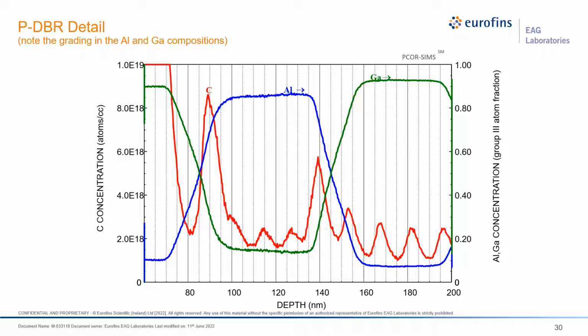As previously mentioned, grading the alloy composition between the low and high index layers can trim the resistance of the DBR. With our PCOR-SIMS technique, it is possible to hone in on this part of the structure with a higher depth resolution profile of the top 200 nanometers of the sample and reveal the composition grading. This occurs because the aluminum and gallium are not simply switched on and off, but varied in a precisely controlled manner to optimize the optical and electrical properties of the interfaces. You can see how the sloping blue line of the aluminum is not straight. It's actually formed in 2 discrete steps going up and 2 discrete steps going down. Measurements with PCOR-SIMS have determined the aluminum content correctly over the entire range of composition from 8% to 83% aluminum. The accuracy of these measurements has been verified using the standard reference material 2841, which I showed earlier.